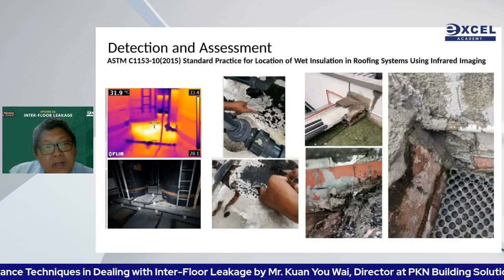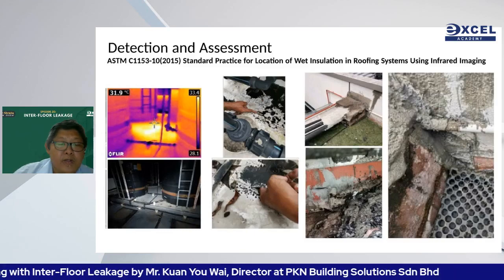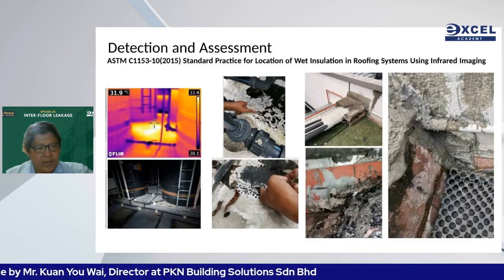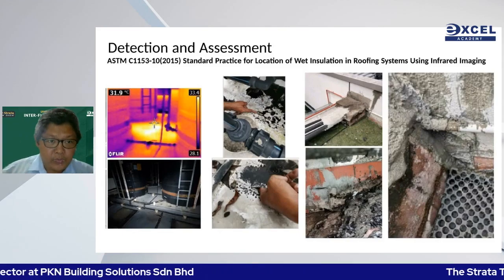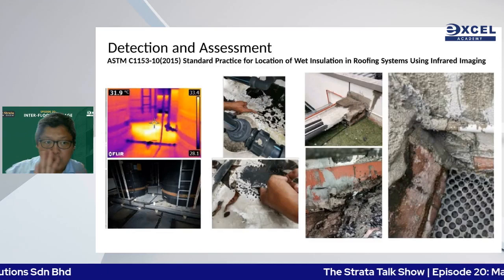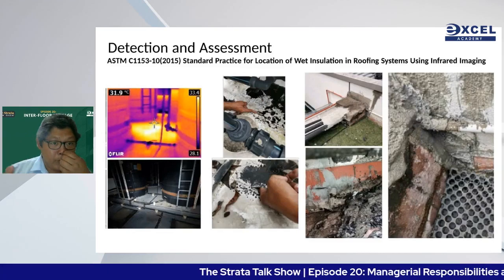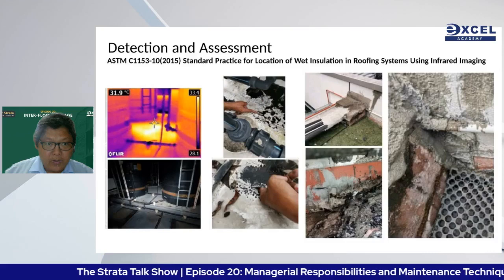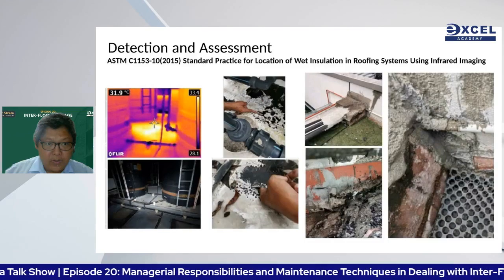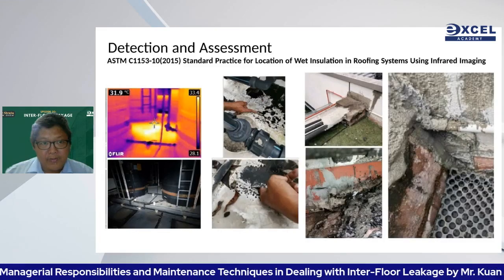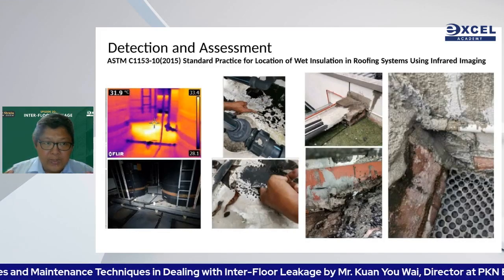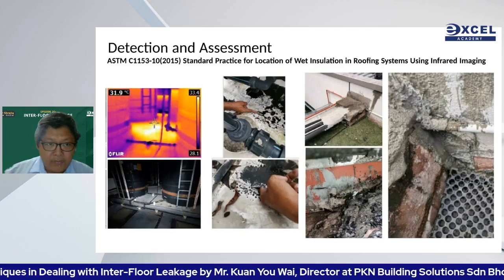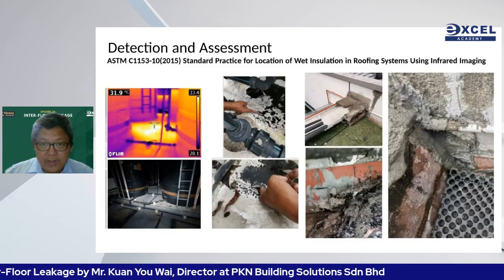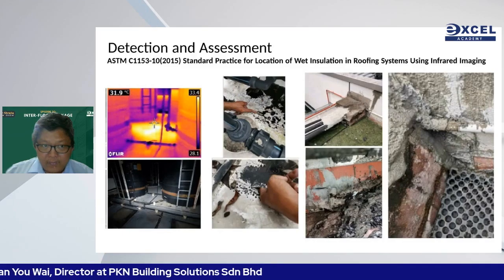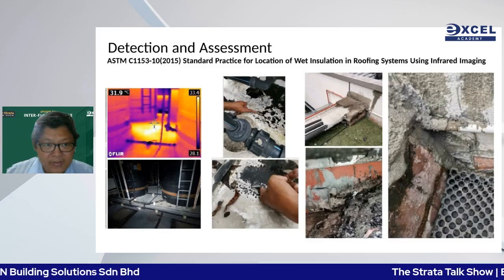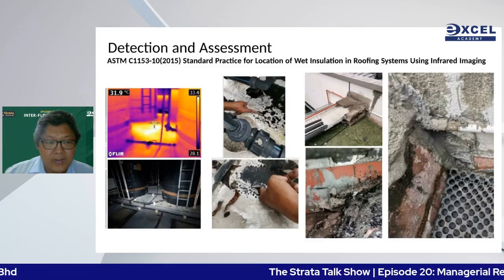And this is one of the sites where I use infrared imaging. You see, compared to dry and wet concrete due to waterproofing failure, on the surface there is no surface-bonding water, because the water is inside the concrete. So under the hot sun, when dry concrete and wet concrete absorb the same amount of heat, in the evening the heat will dissipate faster in the dry concrete area, but in the concrete area with a water pocket underneath the surface, it becomes hotter, simply because water can retain the heat longer as compared to dry concrete.